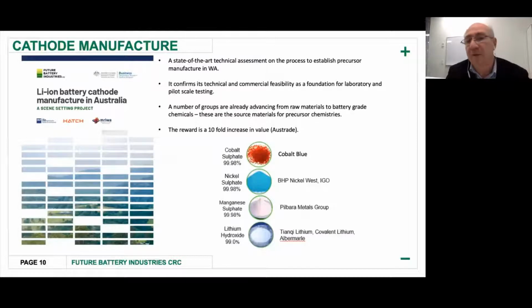An example in cathode manufacture is that the CRC has commissioned a state-of-the-art technical report for the assessment and process of cathode materials. This report has confirmed the technical and commercial feasibility of forming and starting pilot scale testing here in WA. We look at the different minerals that are being produced, and we find that there are already groups that are advanced in producing some of these raw materials, particularly materials like cobalt, nickel, manganese, and lithium.